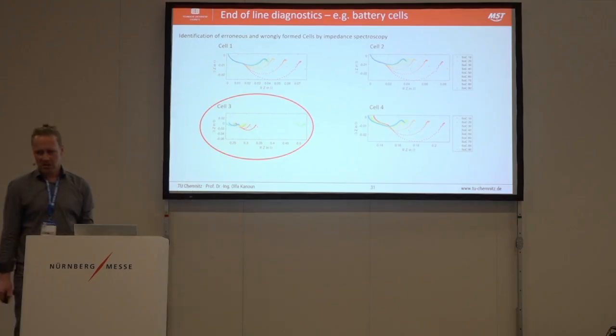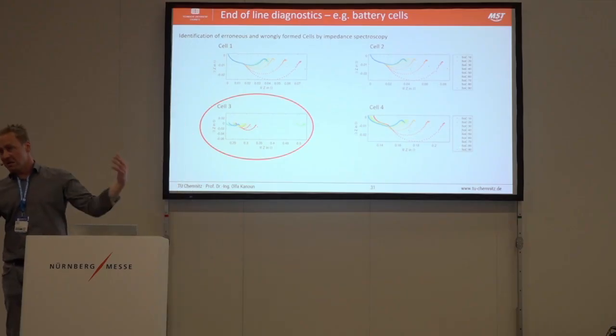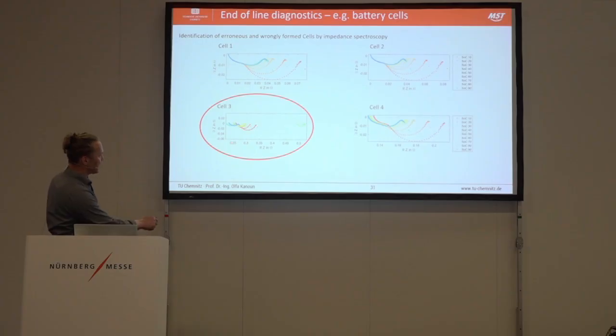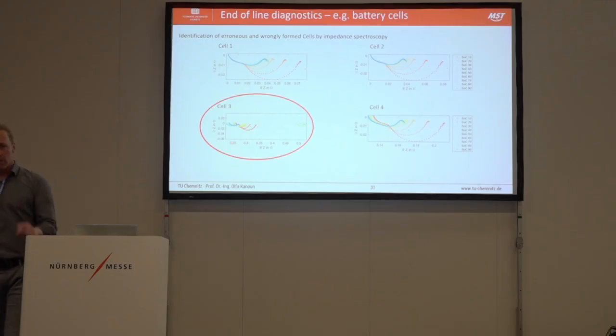You can ask yourself, does it matter? But if you take a look here, this is the real part. The real part is causing heat losses. That means this cell has double the heat loss of all the partners in the stack, and this can become critical. We have a source for a hotspot, and a hotspot in the battery system is almost always critical.